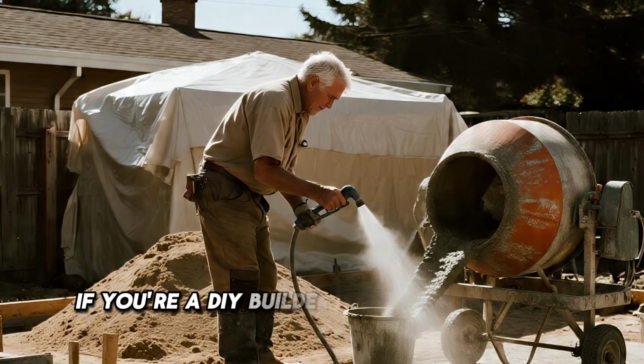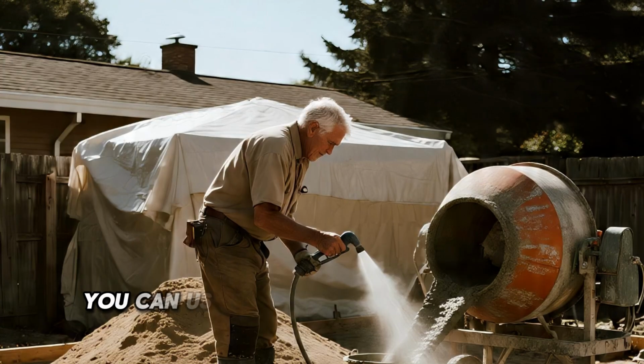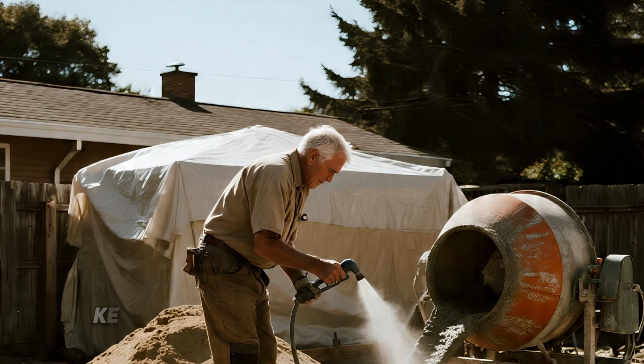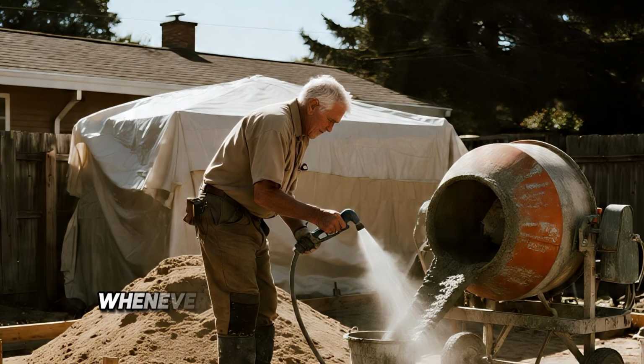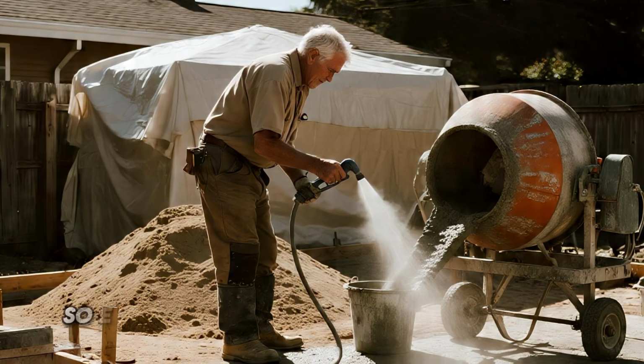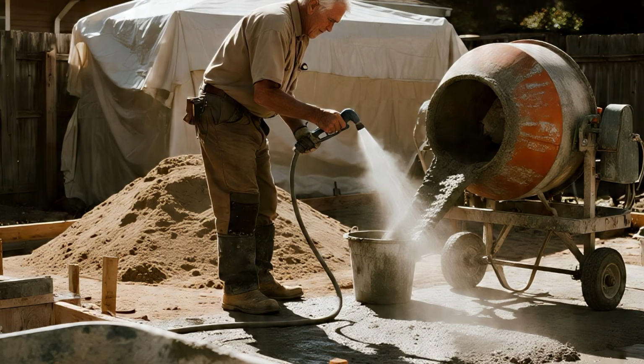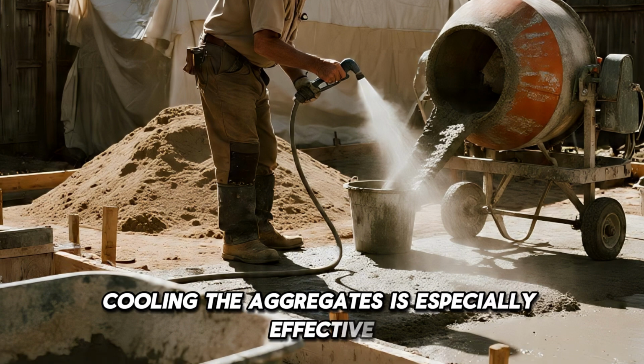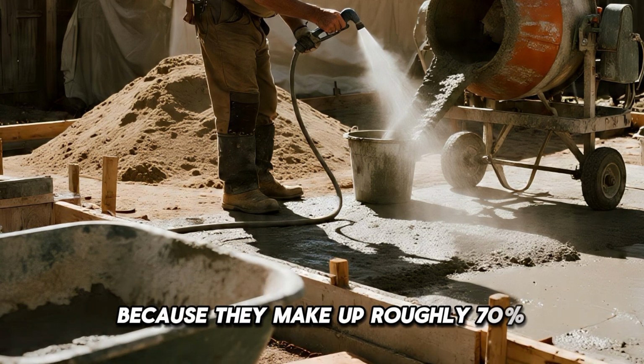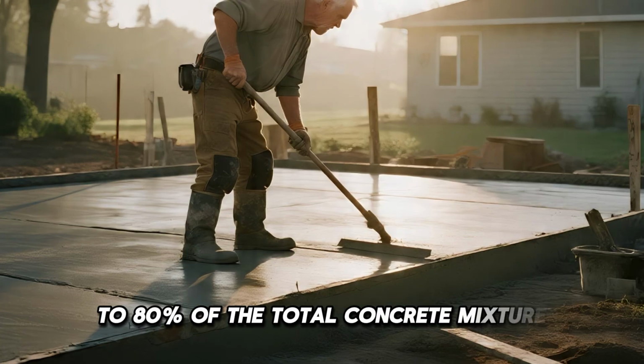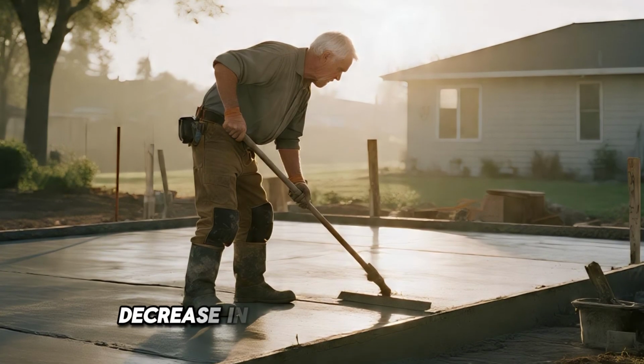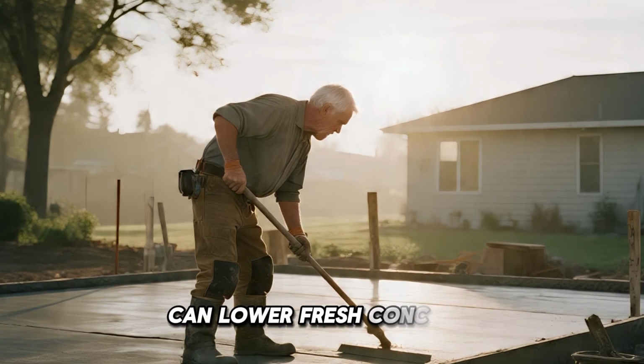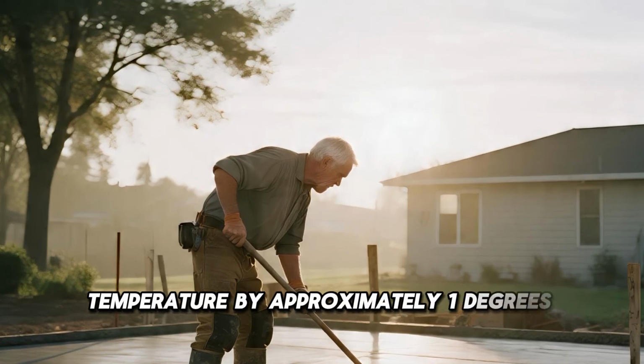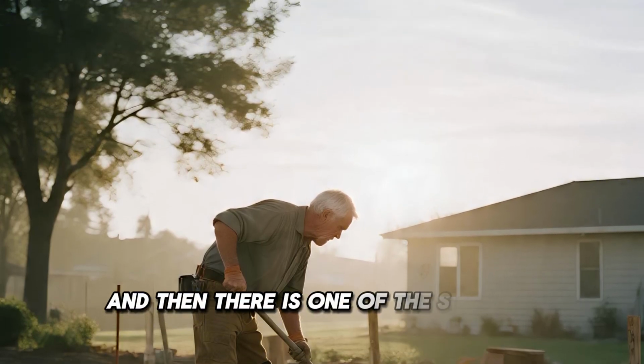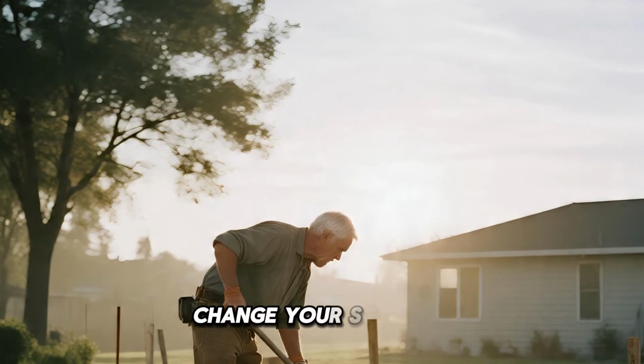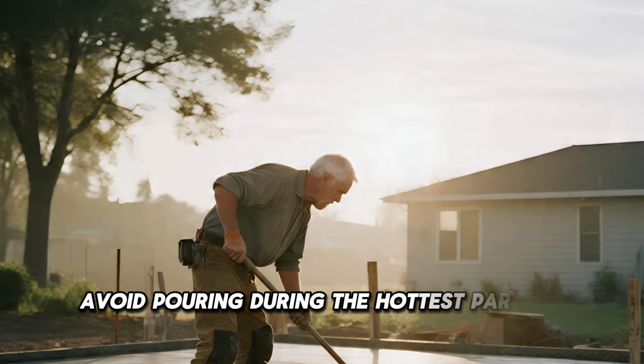If you're a DIY builder mixing concrete on site, you can use the same principle in simpler ways. Keep your sand and gravel piles shaded whenever possible, or spray them with water so evaporative cooling can pull heat away. Cooling the aggregates is especially effective because they make up roughly 70% to 80% of the total concrete mixture. A 2 degrees Fahrenheit decrease in aggregate temperature can lower fresh concrete temperature by approximately 1 degree Fahrenheit. And then there is one of the simplest strategies of all. Change your schedule. Avoid pouring during the hottest part of the day.